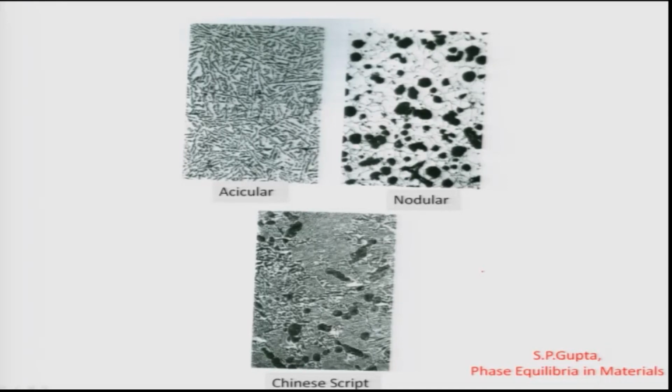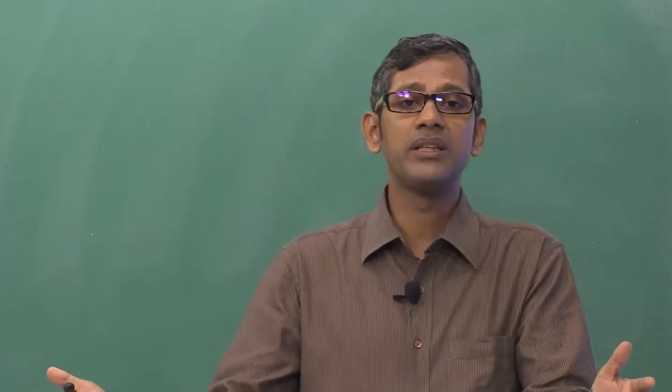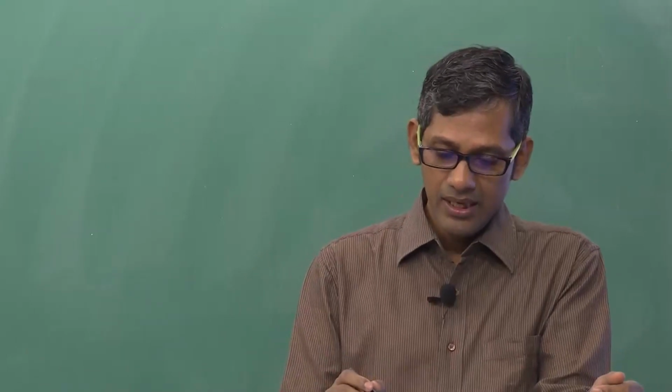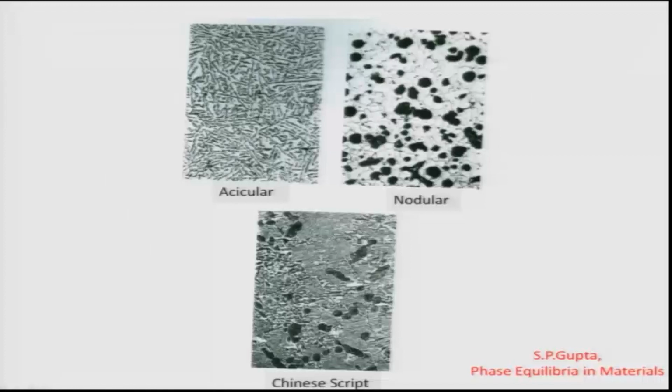Aluminum-silicon, which I discussed in the last class also, is a very classical system, because these eutectic alloys are used in industry, for example in cylinder blocks of many car engines, and the eutectic morphology is known as acicular. The continuous white phase is the aluminum solution, and these long fiber-like features you see here in black color are basically pure silicon fibers.